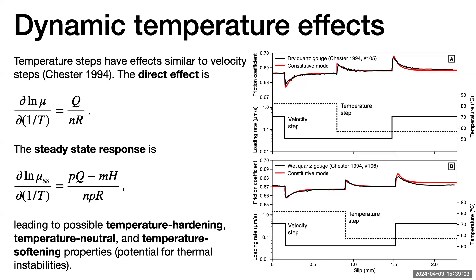The direct effect — the change of friction with temperature — depends on the activation energy for sliding. At steady state it's the difference of activation energy for sliding and activation energy for healing. When you warm a material it should always be softer, yet it's not always — because heating also activates healing, so the material softens and hardens simultaneously. Only the difference between these two effects controls the final strength. That's why the effective effect of temperature is small — but only small after two large compensating effects. There's a direct effect, evolutionary phase, and final steady-state response to temperature.